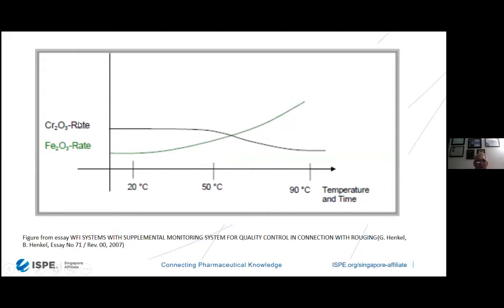This particular graph shows the development of chromium oxide, which is the oxide known as a passivation layer. That passivation layer is only 2.5 nanometers thick. It's a very, very, very small thin layer. It's not a firewall. And it decreases as the temperature increases. And notice that the ferric oxide rate, this is showing hematite, increases sporadically from 20 degrees C and gets exponentially higher after 50 degrees C into almost 90 degrees C. So both the ferric oxide and the combination with the hydroxyls production is why the rouge is so prevalent in hot water systems.